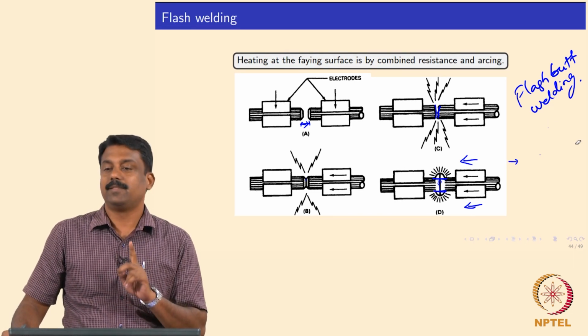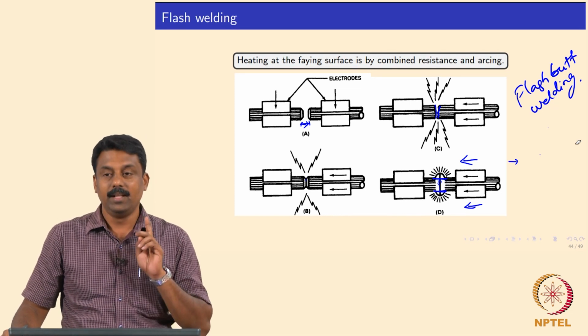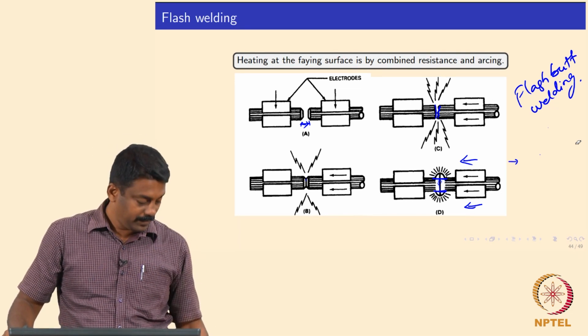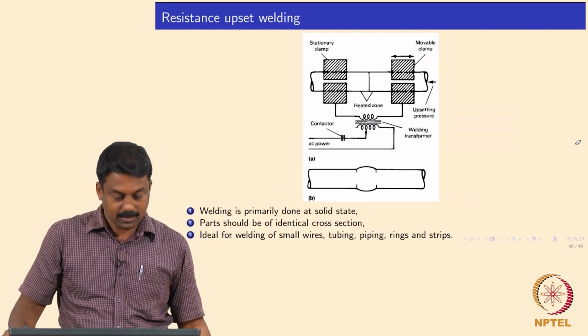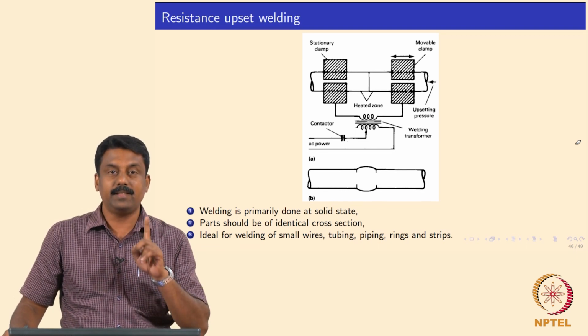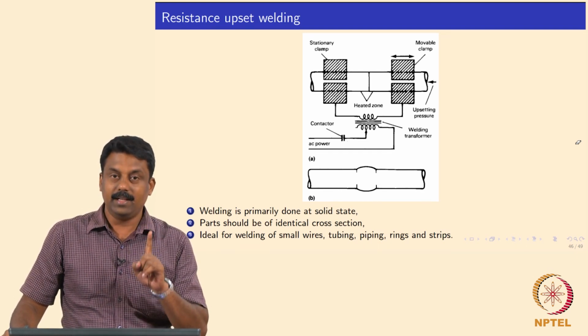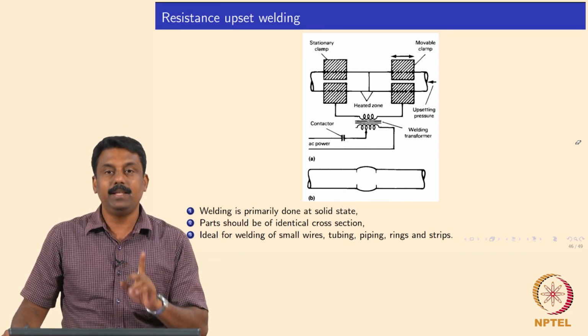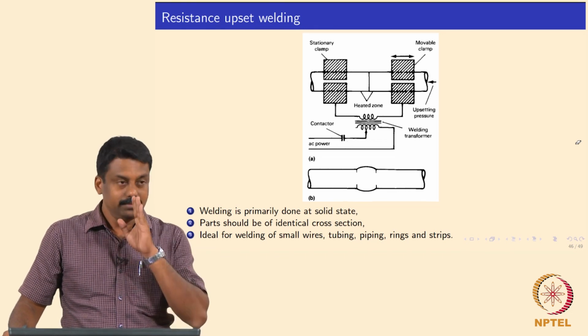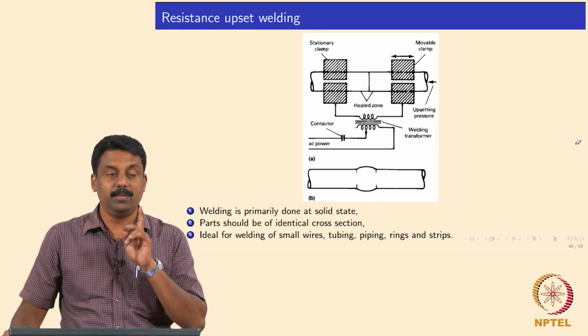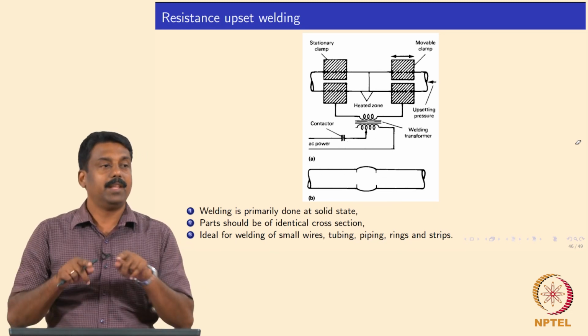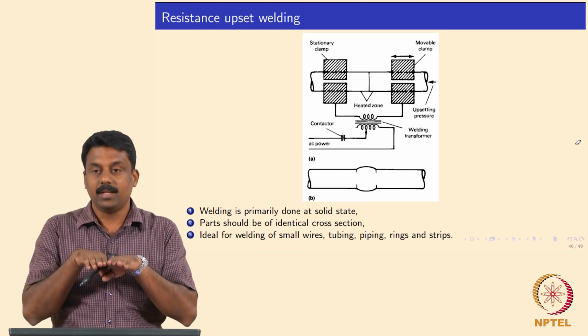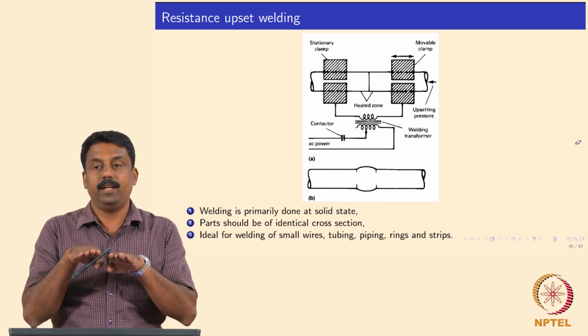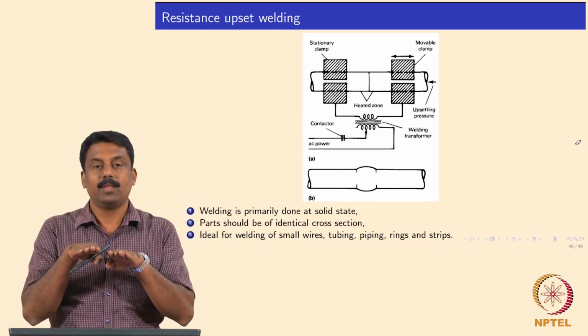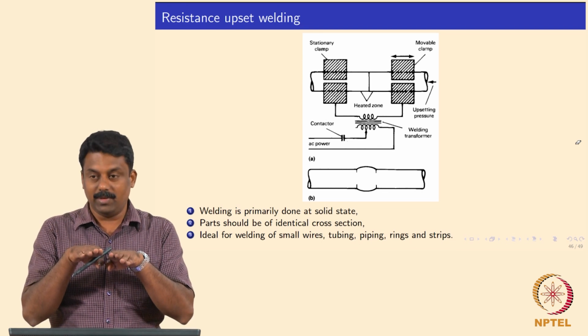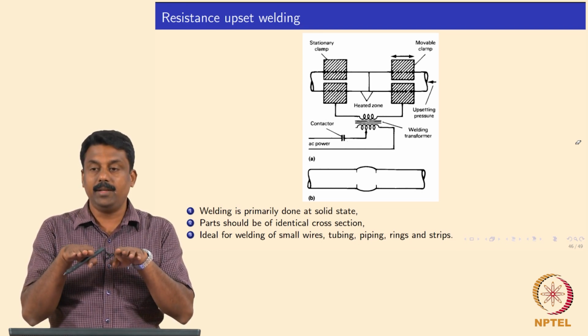And there is another variant of resistance welding which is similar to flash butt welding, known as resistance upset welding. The difference between resistance upset welding and flash butt welding is that in resistance upset welding we do not arc, we do not melt the interface. In flash butt welding, it is important to understand the difference: the interfaces are not kept close to each other. There is always some gap maintained in the beginning, so that we can form an arc. So arcing is important, the interface will be molten, and then you do an upsetting.